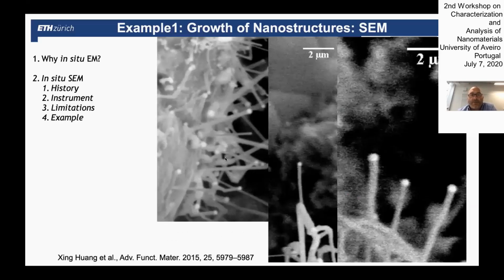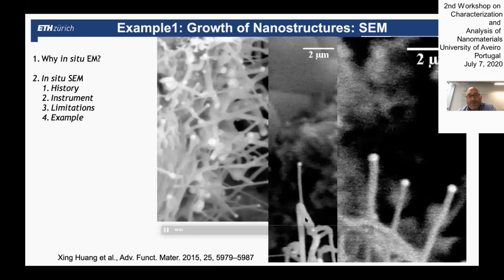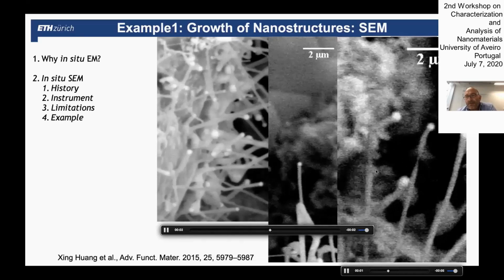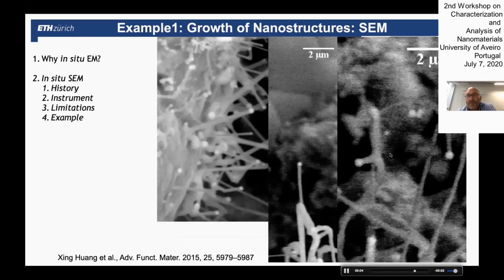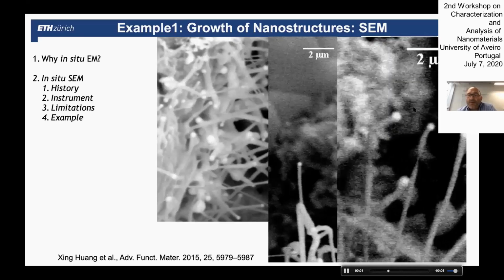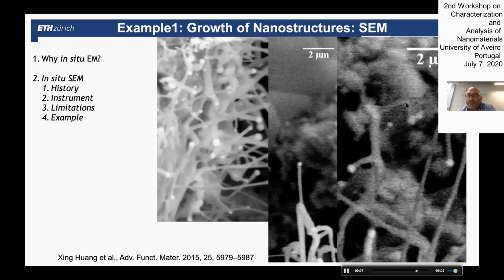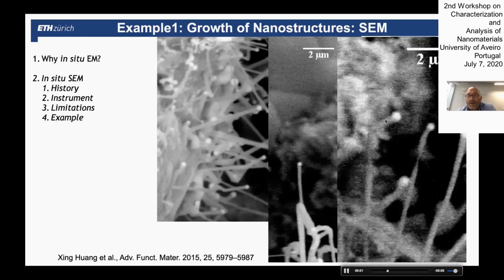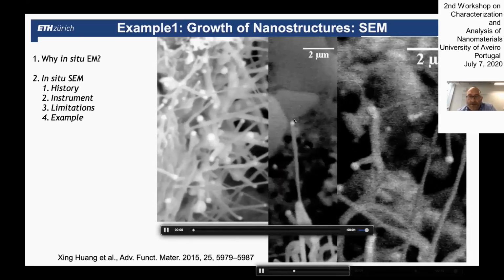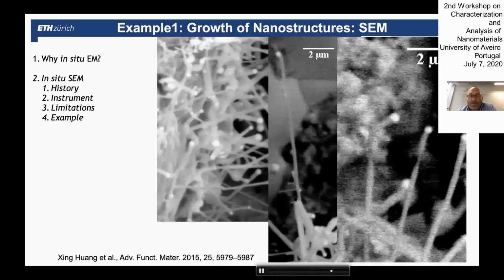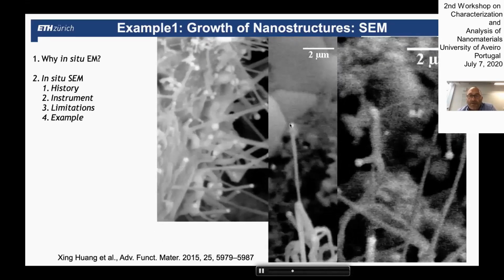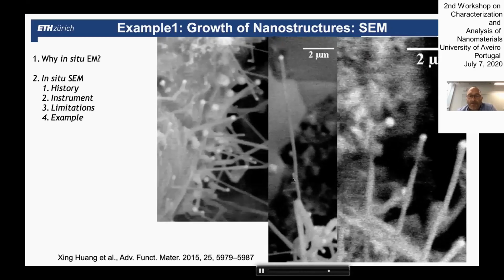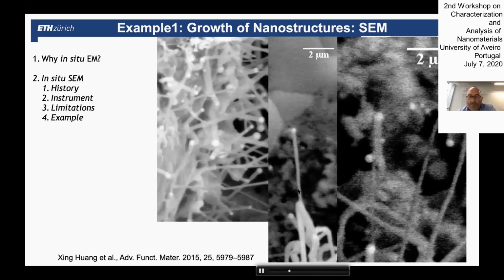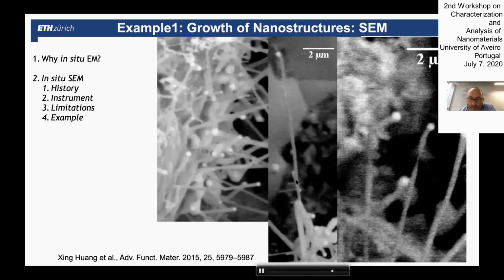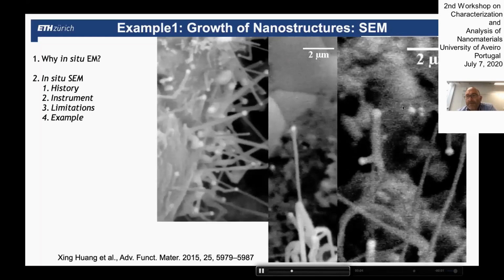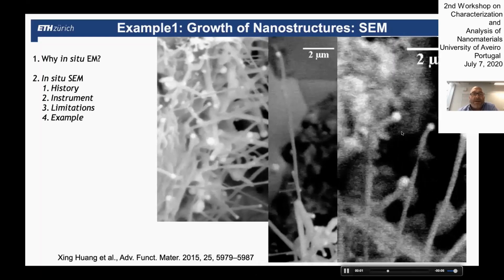And then it was quite beautiful because we could see the growth of these beautiful nanowires, and we could study a bit by directly visualizing it. We could study what kinds of processes lead to the branching of these wires. So you see there's a wire growing, and at one point there are sub-wires growing. And here's another video where you can see that. The catalyst particle is a silver particle, but during growth sometimes this catalyst particle loses some parts, and they can then remain on the rod that is growing. And when these remaining parts migrate to the surface, they can induce additional branches of this nanowire. So it's a beautiful study.